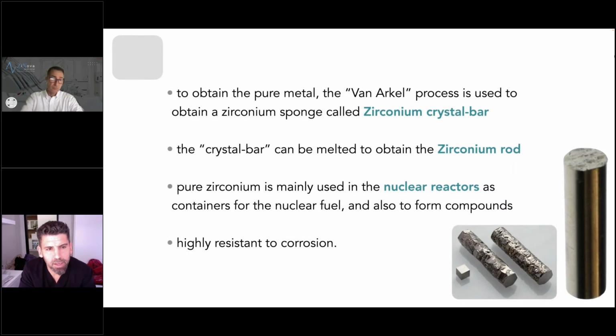Once we obtain that sand, we can obtain the pure metal, the zirconium, via a process called the Van Arkel process. And with that, we extract the zirconium from the mineral, and we obtain a zirconium crystal bar. And then this bar can be melted to obtain zirconium rods. Pure zirconium is mainly used in nuclear reactors as containers for nuclear fuel, and also to form several compounds because it is highly resistant to corrosion.